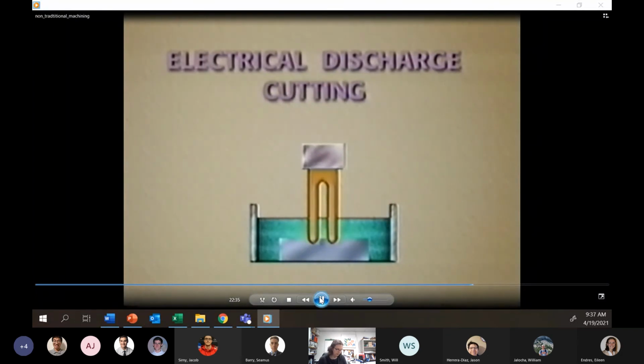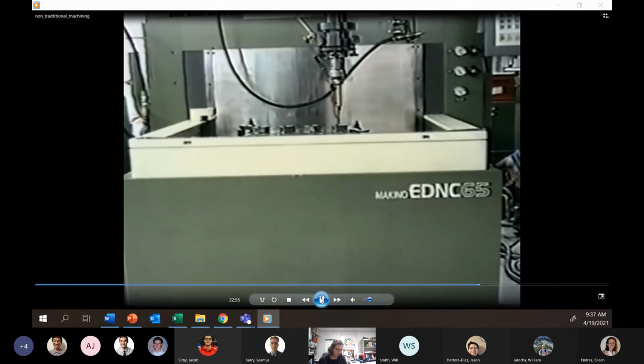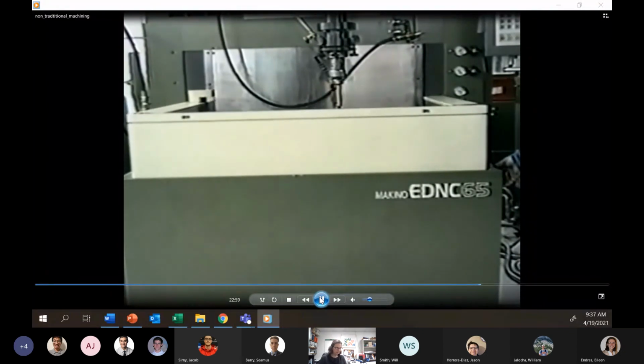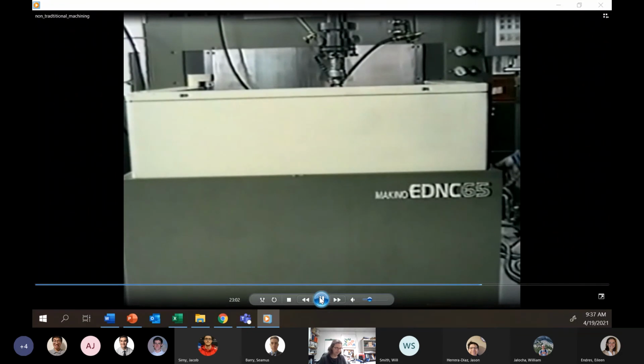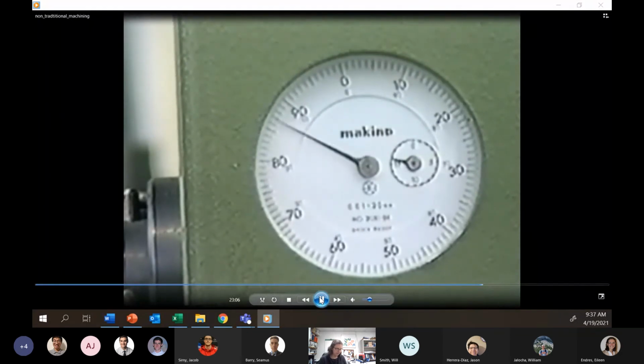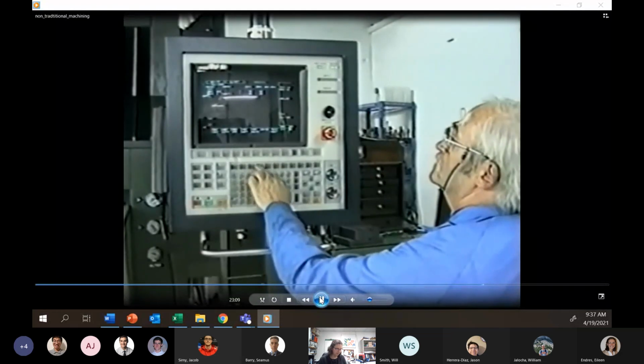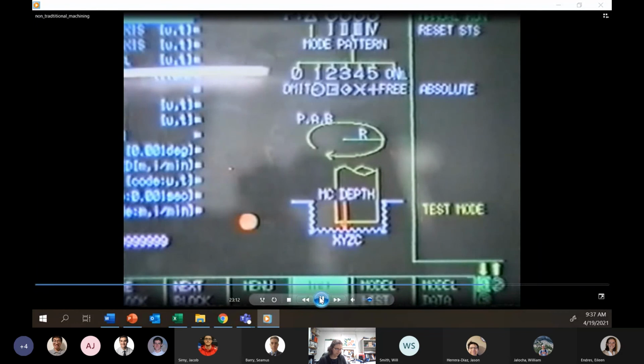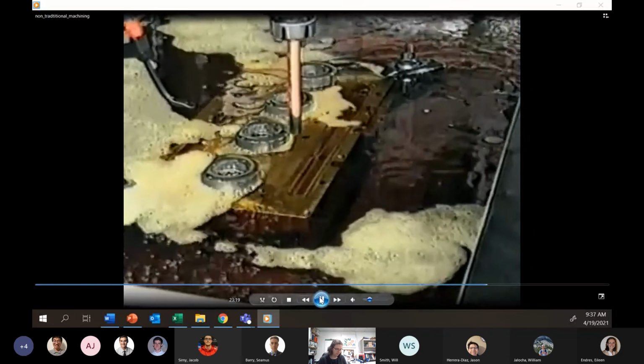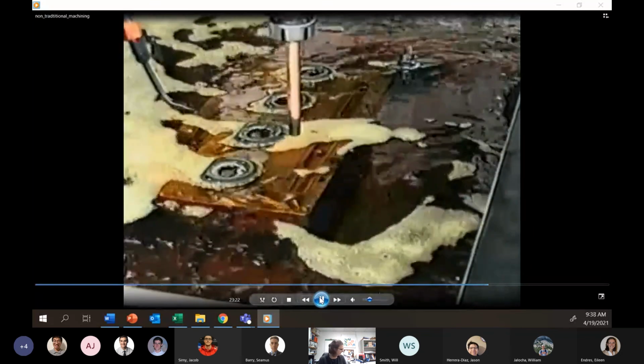A new method of flushing out the debris from the machining process is to move the electrode away from the work and then down again. Resume machining for a few seconds and then move the electrode away again. This causes a very efficient flushing of the surfaces, leading to an increase in the cutting rate and a decrease in the rate of electrode loss and hence better shape definition. The electrode can be rotated like a milling cutter, and the CNC controller moves the electrode around the shape to be machined. This gives rise to improved surface finish.